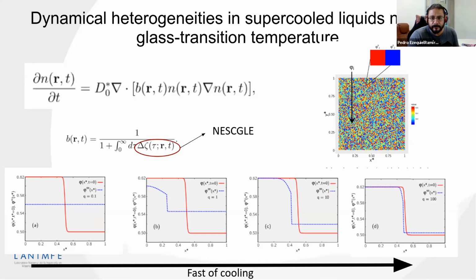In the plots at the bottom of the screen, we present the density profile through the adjacent cells. Red lines describe the initial condition where one cell has a different density than the other cell. The blue line is the final stationary state after a cooling process. Actually, a horizontal final state means that the density is the same for both cells, which is expected for equilibrium states. In contrast, non-horizontal final states mean arrested densities among cells. Therefore, dynamical heterogeneities are present. We observe that the theory predicts that such dynamical heterogeneities depend on the cooling rate. Slow cooling rates promote a homogeneous density between cells, while fast cooling rates promote non-homogeneous final states.